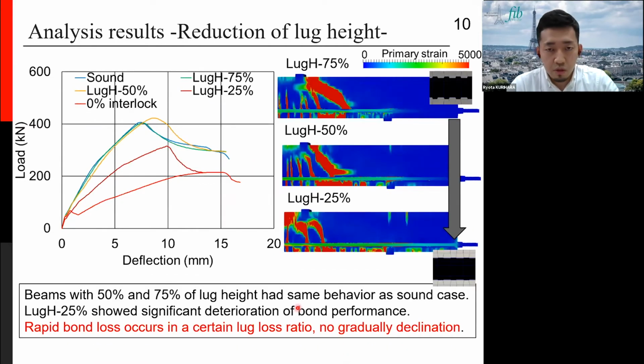Next, let's focus on the reduction of lug height. The green and orange lines, the cases with 75% and 50% of lug height, show almost the same behavior as the sound beam in the load deflection curve and the strain distribution. On the other hand, in the case of 25% of lug height, the stiffness decline, the crack concentration, and the non-uniform rebar strain distribution were clearly observed. So bond was deteriorated significantly, although clear rebar slip was not observed in this case.